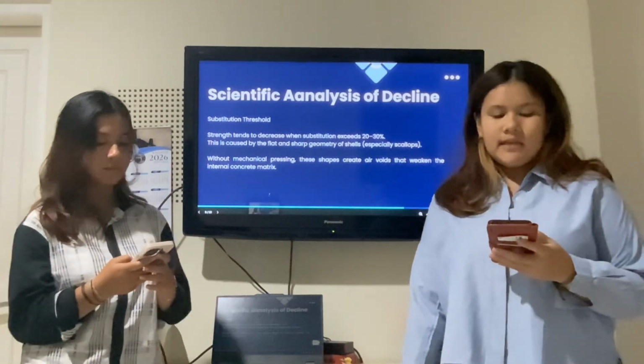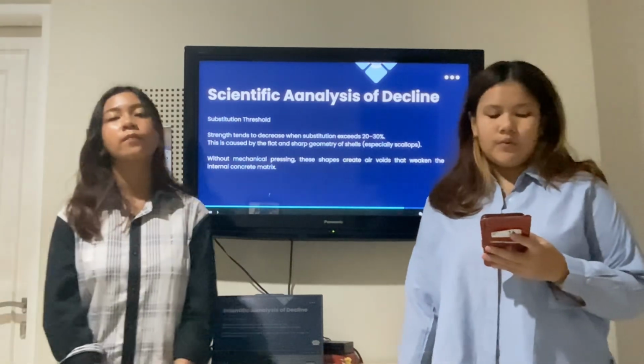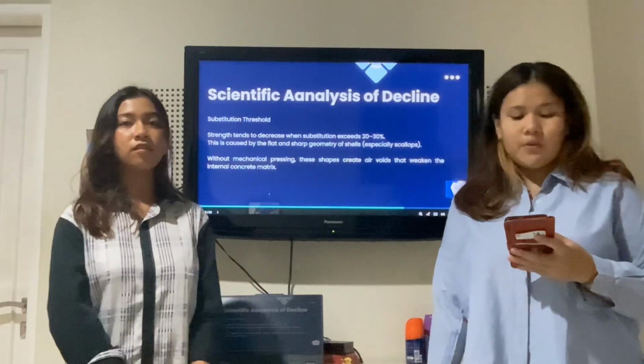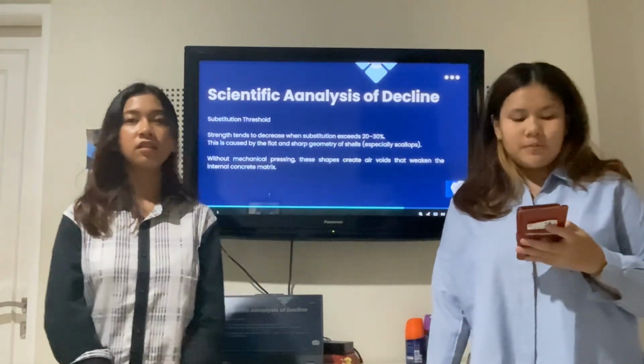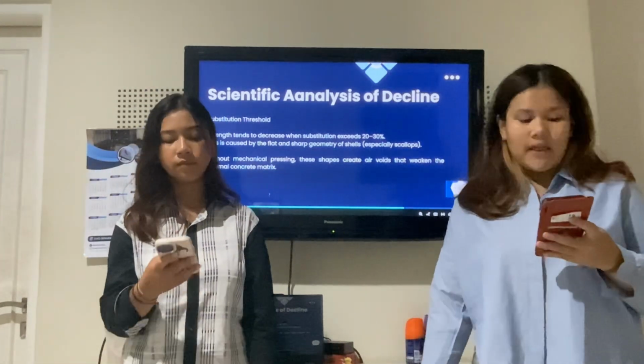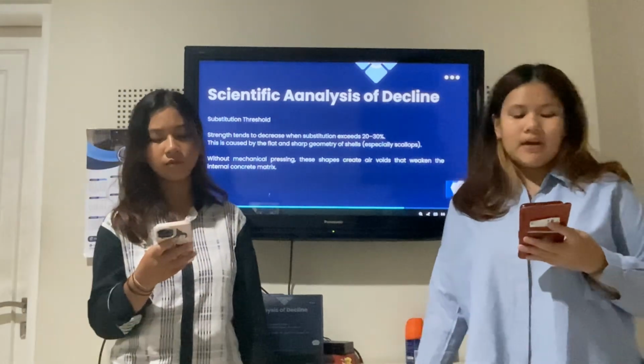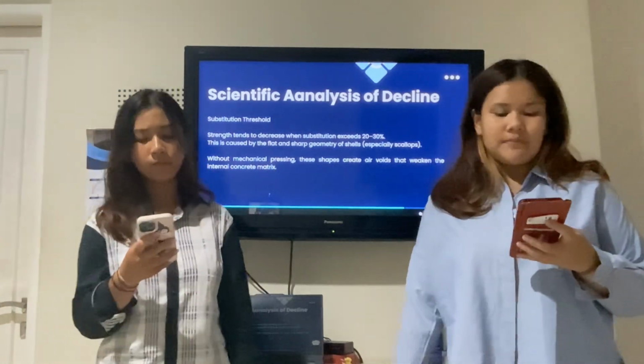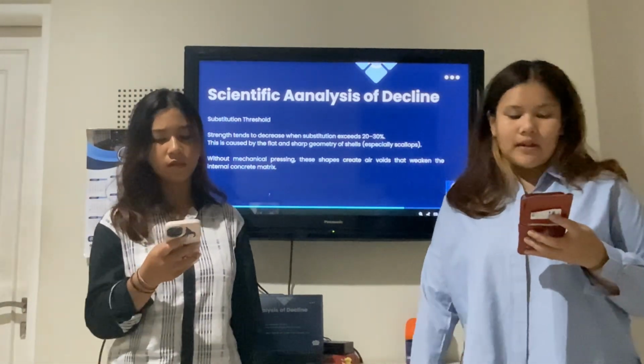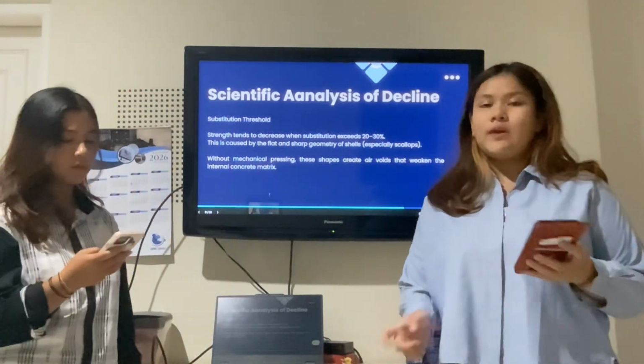However, there is a threshold. Beyond 20%, the strength drops. Why? Because the shell particles, especially from scallops, are flat and sharp. Without heavy mechanical pressing, the shapes trap air, creating micropores that weaken the structure.